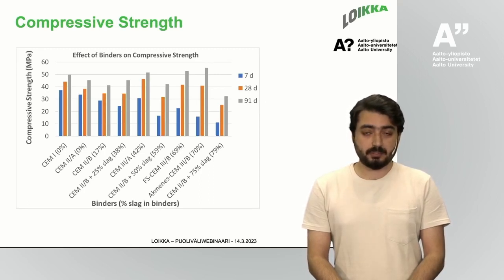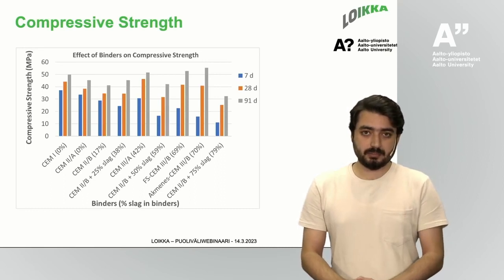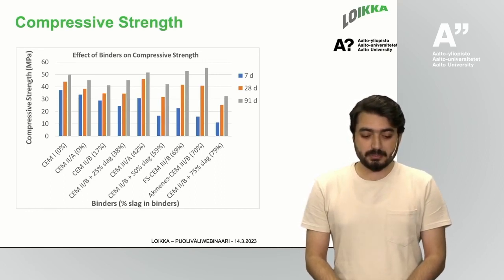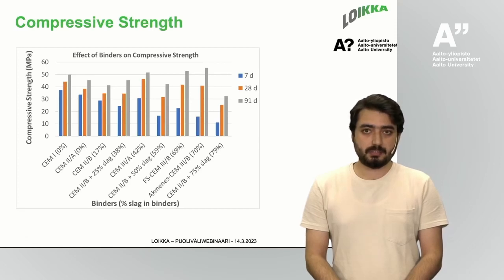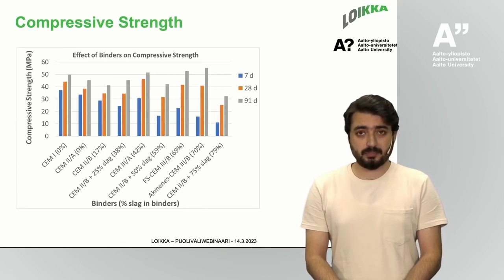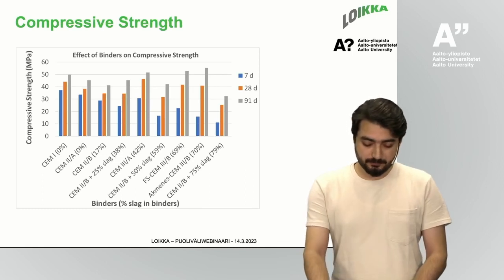Then if we look at the 91 days, it shows the incremental increase, and CEM III/B achieved the highest compressive strength, even more than CEM I. And if we look at the 28 days, you can see the irregularities. So slag didn't have a direct effect on the compressive strength.